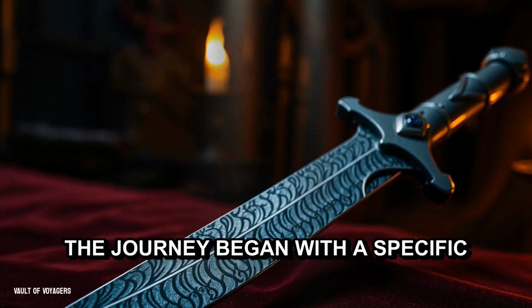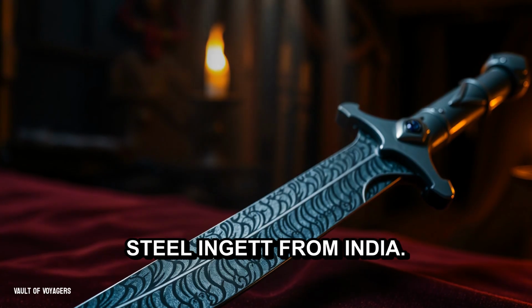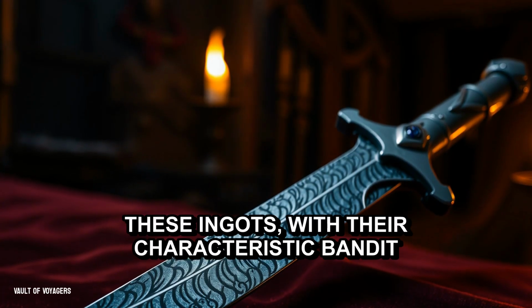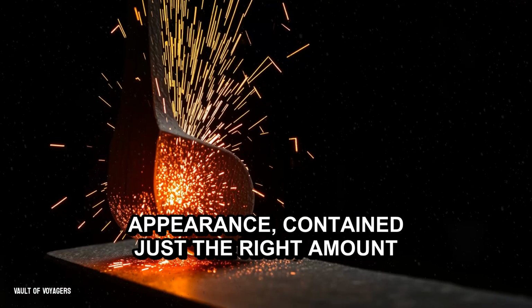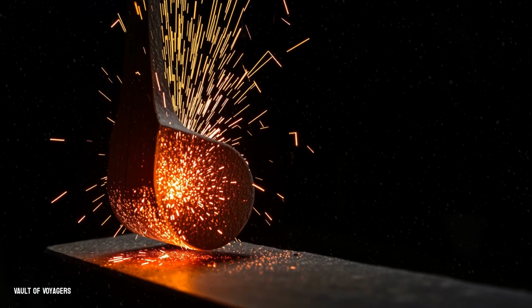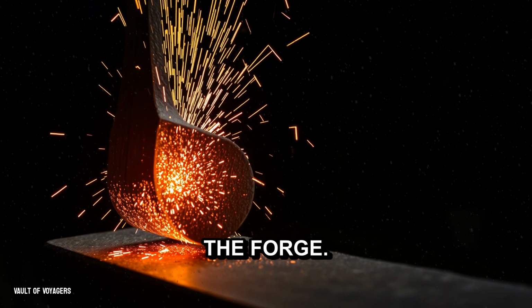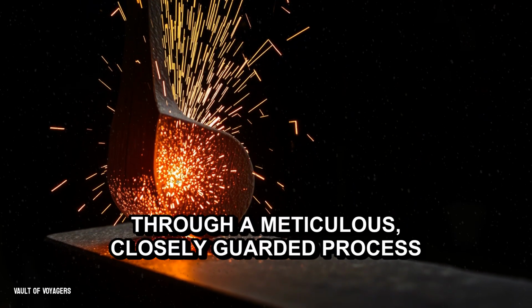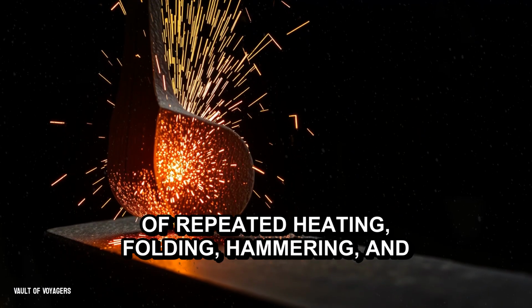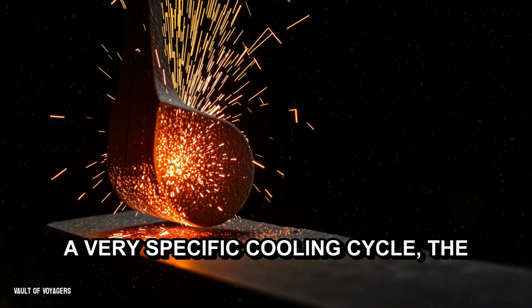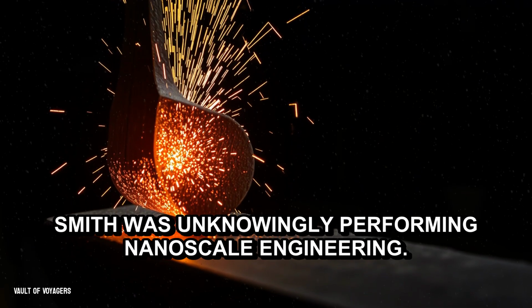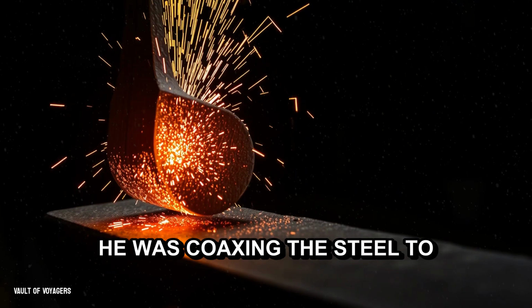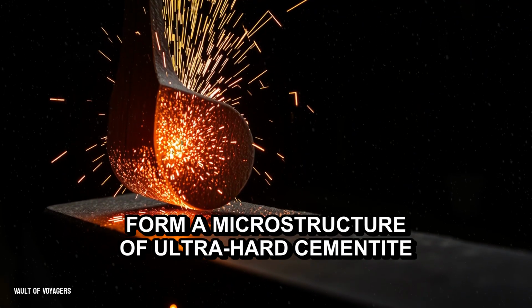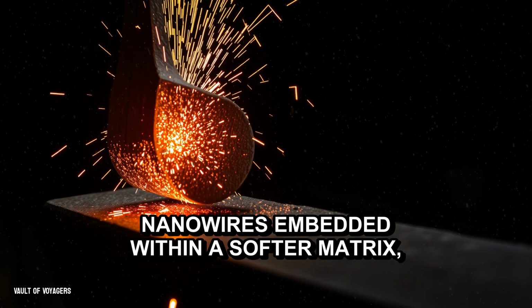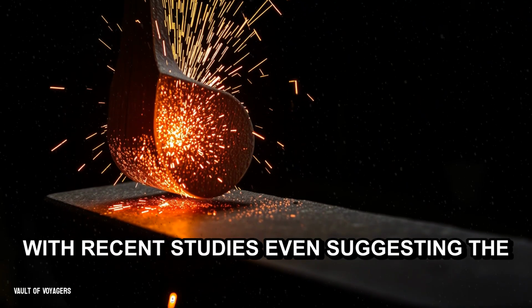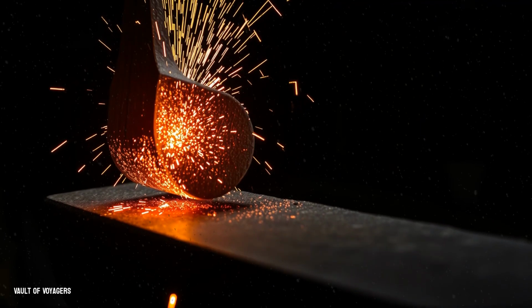The journey began with a specific type of raw material, the Wootz steel ingot from India. These ingots, with their characteristic banded appearance, contained just the right amount of carbon. But the true magic happened in the forge. Through a meticulous, closely guarded process of repeated heating, folding, hammering, and a very specific cooling cycle, the smith was unknowingly performing nanoscale engineering. He was coaxing the steel to form a microstructure of ultra-hard cementite nanowires embedded within a softer matrix, with recent studies even suggesting the presence of carbon nanotubes.